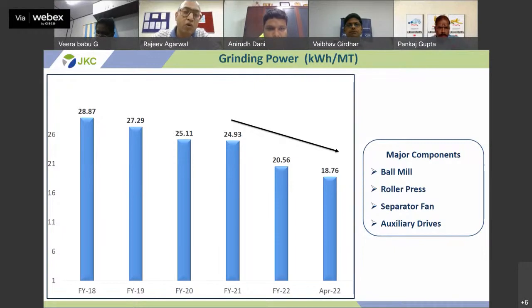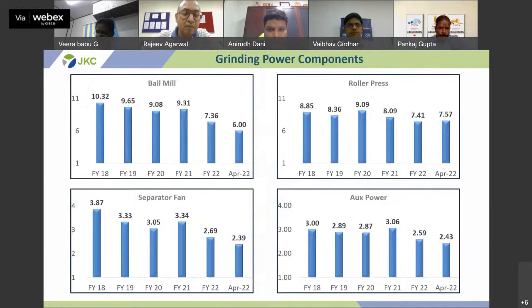So this is our grinding power trend. We can see, sir, the journey from 28 to 18.76. Our major components for grinding power are the ball mill, roller press, separator fan, and auxiliary drives. In the ball mill we reduced the power from 10.32 to 6, in the roller press from 8.85 to 7.57, in the separator fan from 3.87 to 2.39, and auxiliary power is also reduced to 2.43.